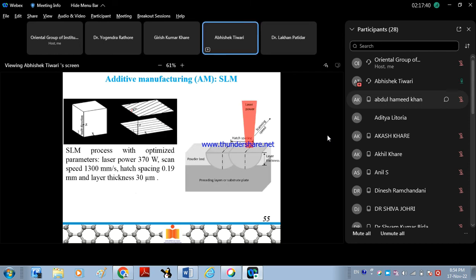So, the SLM process with optimized parameters. Typical process parameters are laser power of 370 watt, scan speed of 1300 millimeters per second, hatch spacing of 0.19 and layer thickness of 30 micrometers. This is the layer thickness of one layer, and this is the hatch spacing. Hatch spacing is when you print one line and then the next line, the distance between the center of these two lines is called hatch spacing.